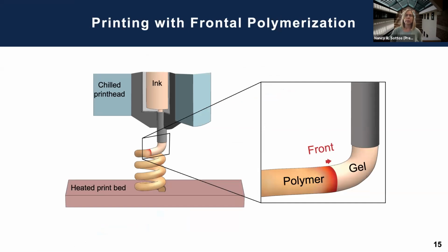It also helps you understand a little bit about how the front propagates. But as I said, if we tune this to work from the gel state and then chill it in a print head, we are able to 3D print. We use a heated print bed to trigger the front. And as you'll see, the front then is able to follow the print head, and we're able to cure in real time and basically 3D print on the fly.